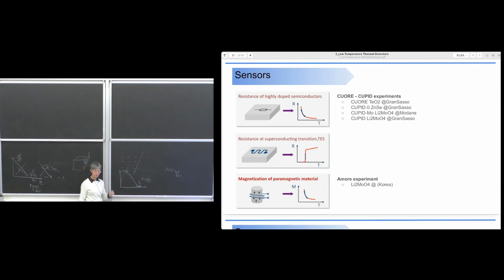But since our signal is very slow, it happens that even if we are discussing a half-life like this, we can see pile-up events due to this two-neutrino double beta decay. Nobody believes us when we say something like that, but you can have two pile-ups. If you take two signals here, and you assume that they are really emitted simultaneously, you just have a pulse which is much higher, with an energy that corresponds to the sum of the two energies, and so there is a count over here.